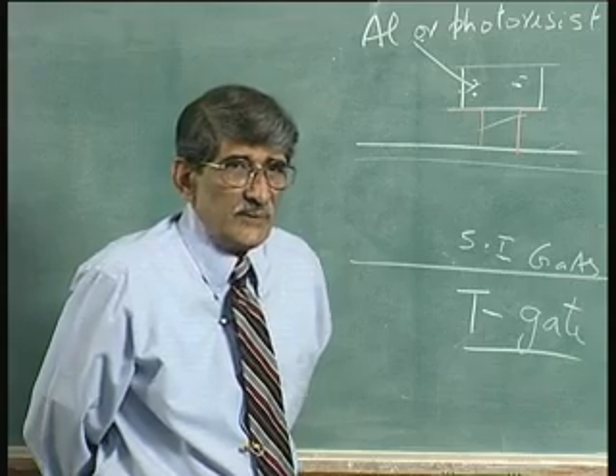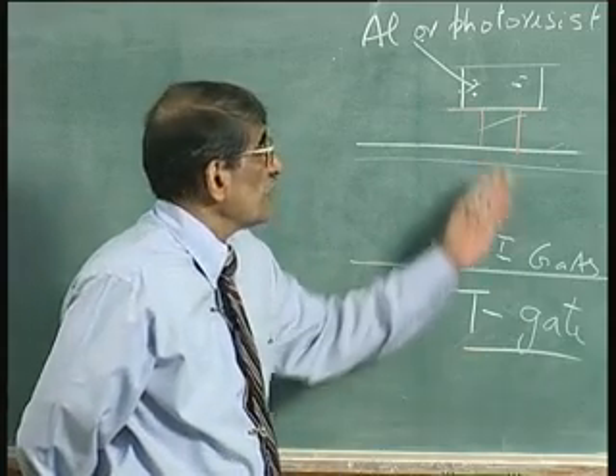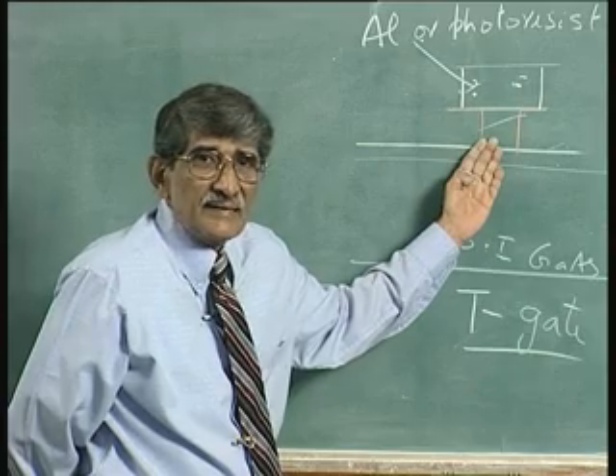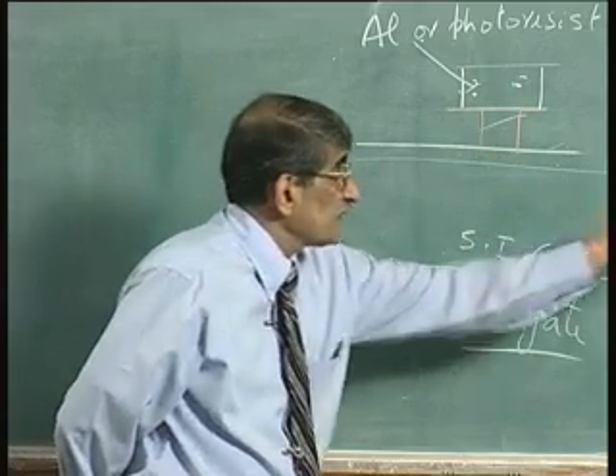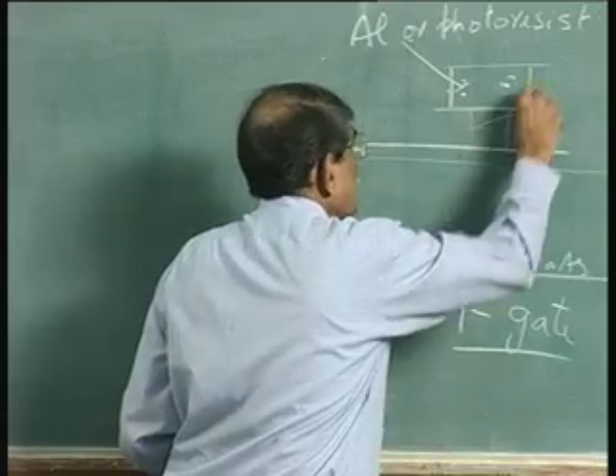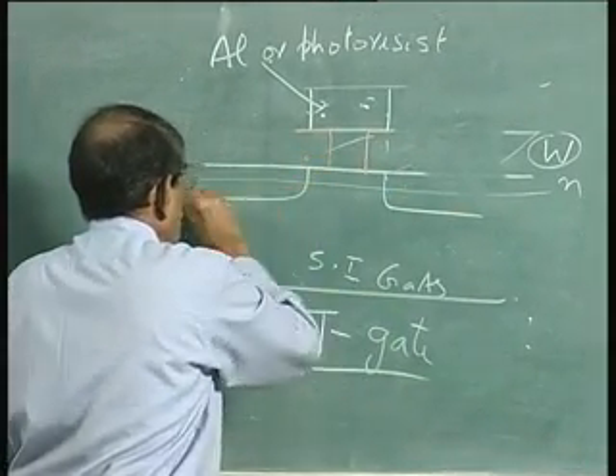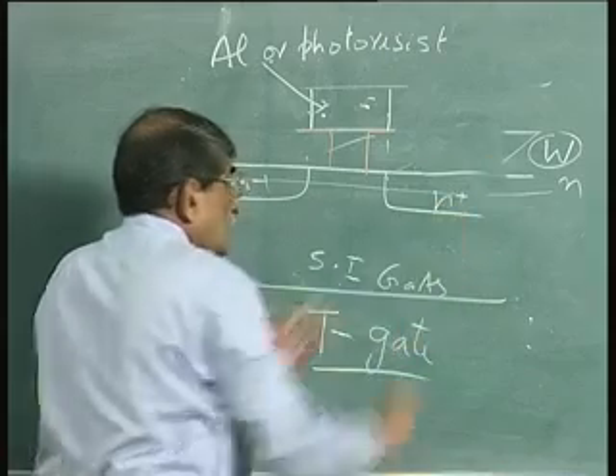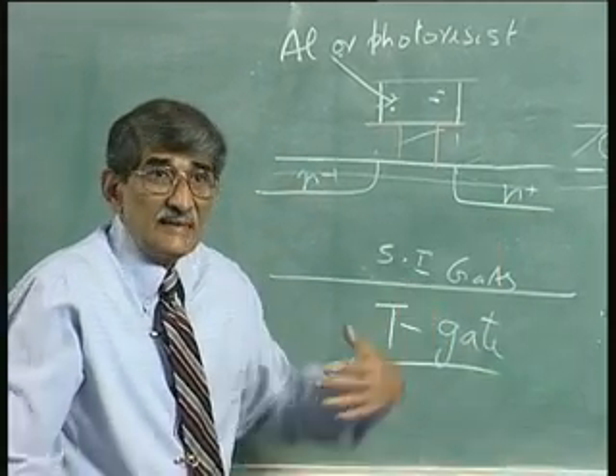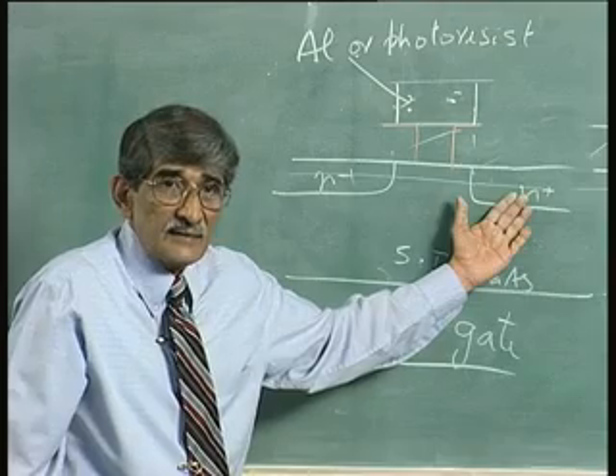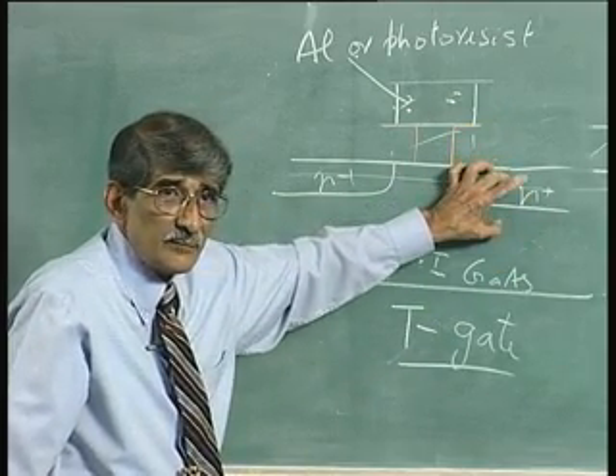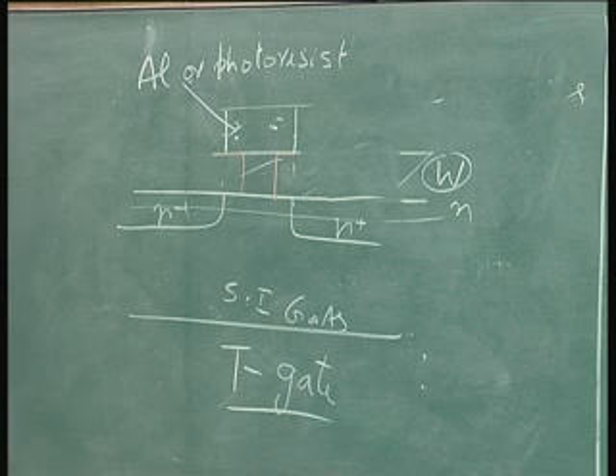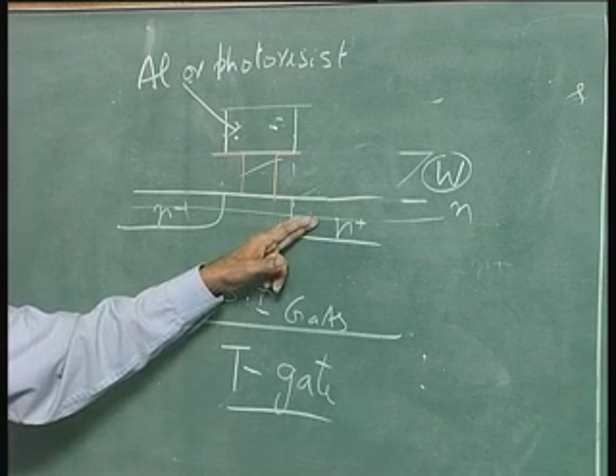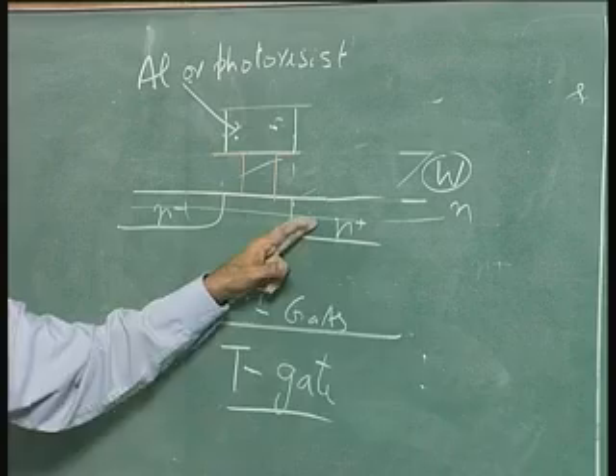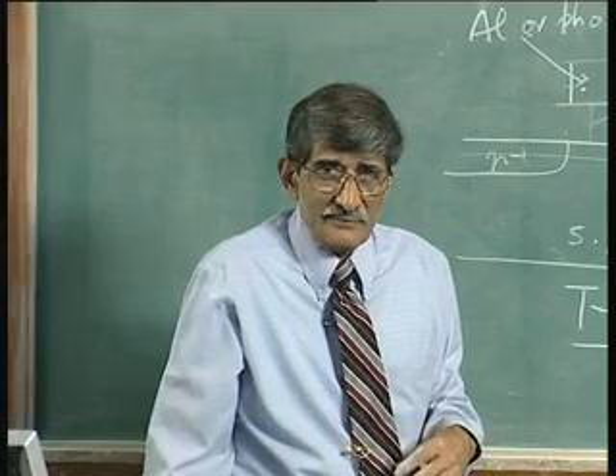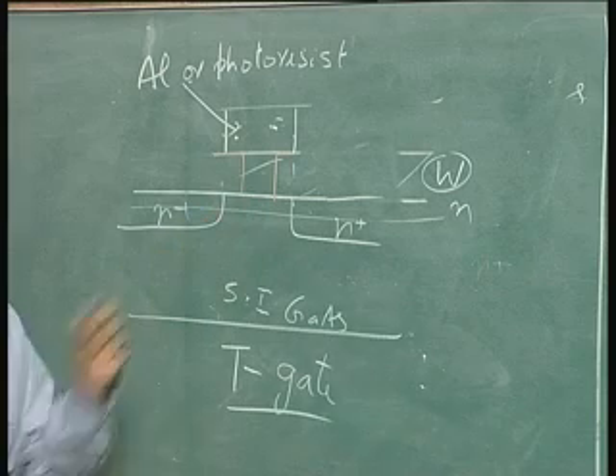The only problem that you have here is the use of tungsten, a refractory metal. You need that, because after you do this implantation onto this N plus portion, you have to subject it to annealing at about 700 to 800 degree centigrade to recover the damages which have been produced, to push the dopant atoms into lattice sites, all that you have to do. Okay. So, people were looking into other methods of obtaining self-aligned structures.